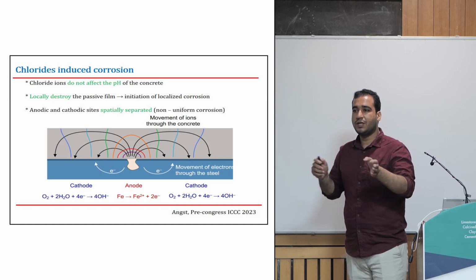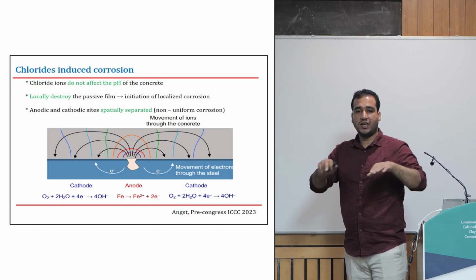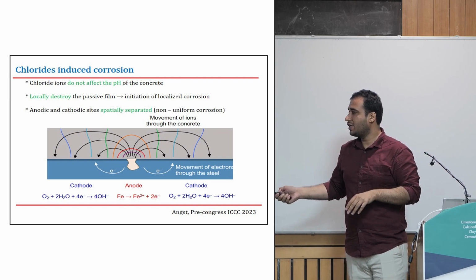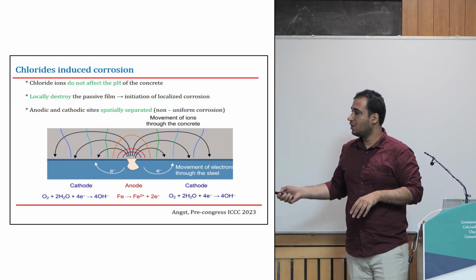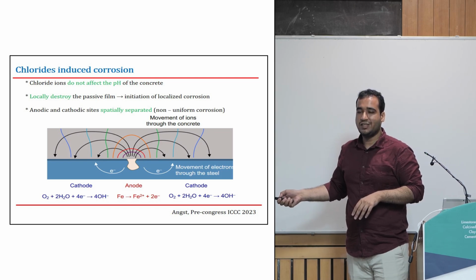There, in carbonation, both were near to each other and widespread. Here the cathodic area is much larger than the anodic area. So whatever the potential is, it is driven by this region only. That's why we observe more pitting type of corrosion.